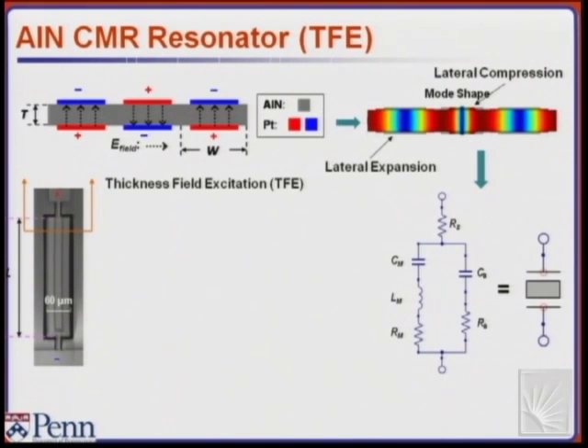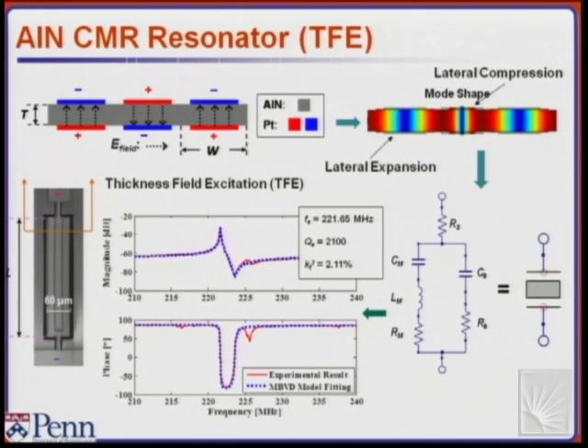Generally, those, C0 and RS, are actually neglected in a macro scale device. In a micro and nano scale, you need to account for those because they can affect your circuit performance. And here's how the model actually fits an experimental curve of a 220 megahertz device with a Q of 2100 and an electromechanical coupling of about 2%. You can see how both phase and amplitude of the admittance response of this circuit fit very well the effective electrical response of the mechanical device.